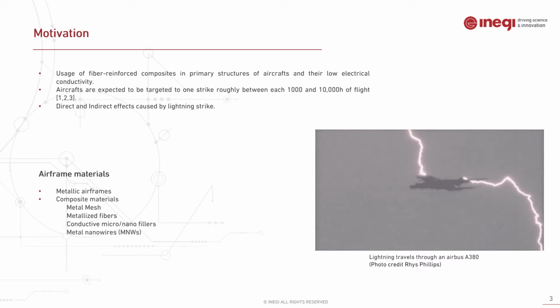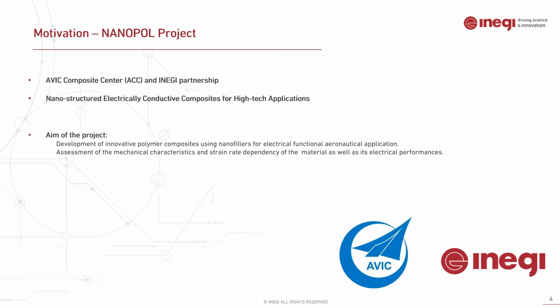nanowires. So to address this issue, the NANOPOL project has been started, which is a joint project between Avic Composite Center from China and INEGI from Portugal. The goal of the project is to develop a multifunctional composite material by interleaving silver-loaded conductive layers into a composite laminate, and therefore it is hoped to increase the electrical conductivity as well as the mechanical properties.